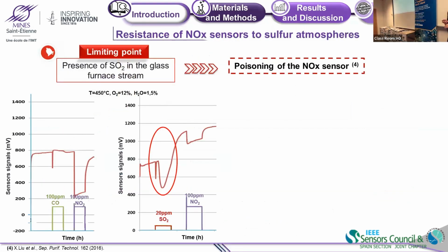The limiting point in the application of glass furnaces is sulfur. Indeed, there is SO2 in the glass furnace stream, and it is poisoning the sensor. As we can see on the graph, in red, is the sensor response. If we inject 100 ppm of CO, there is nearly no response. When we inject 100 ppm of NO2, there is a huge negative response that corresponds to the normal working function of the sensor. And in this graph, when we add 20 ppm of SO2, the response is totally disrupted, and then the response to NO2 is largely lower. So the poisoning of the sensor is confirmed.